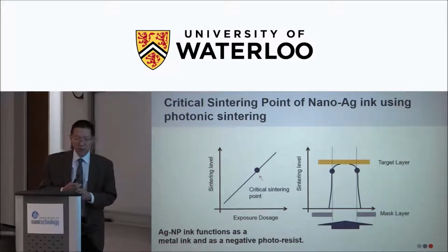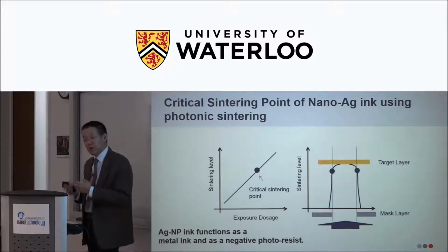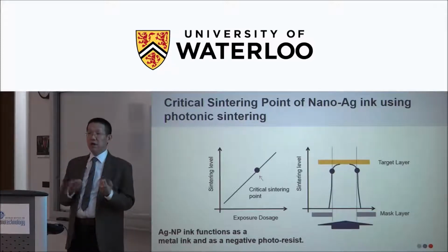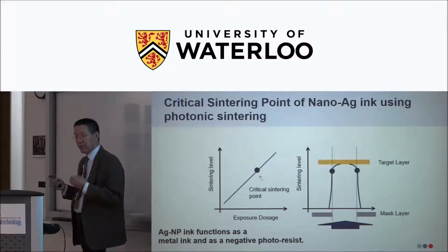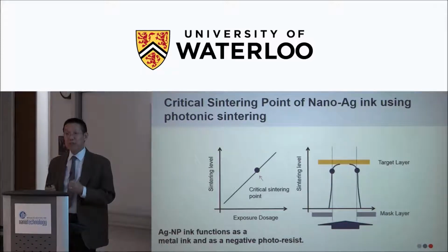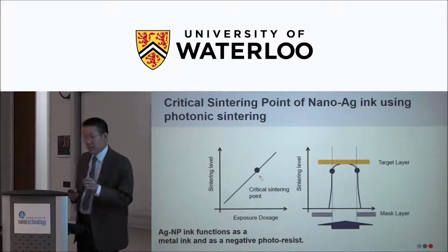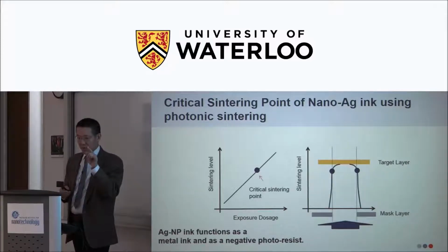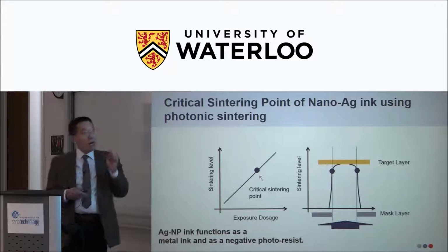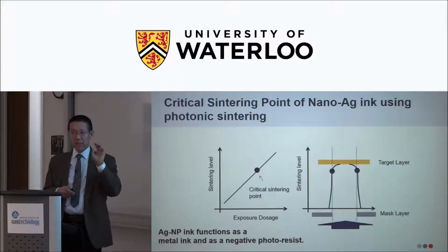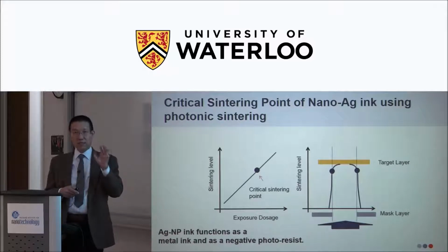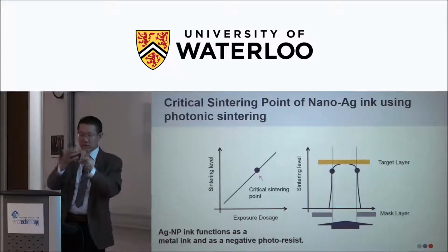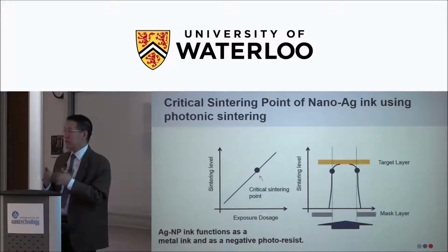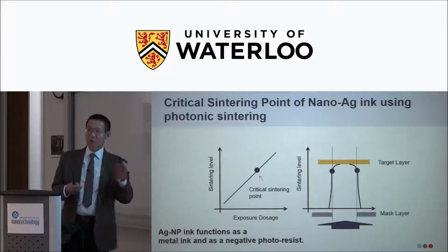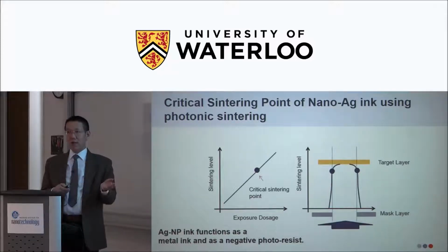Now, we looked around and said, why don't we use a nano silver ink combined with photonic sintering, in a similar way as people use a negative photoresist? Because in nano silver ink there is what we call a critical sintering point. When you use a pulse light to cross-link and sinter these nanoparticles, there's a critical sintering point, above which these nanoparticles are sintered and you cannot remove them anymore. But below that, you can wash them away like usual nanoparticle ink.